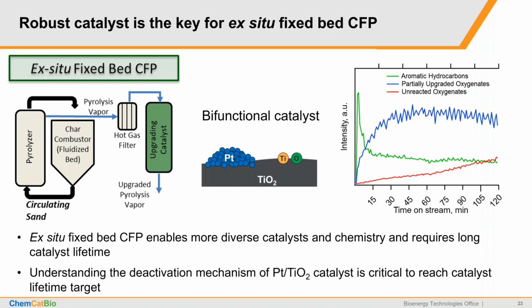However, this catalyst also has deactivation problems, and it will deactivate during single cycle runs, primarily by coke formation. After oxidation regeneration, catalyst activity will be largely recovered, but we do have concerns about long-term stability, and understanding this mechanism will be critical.